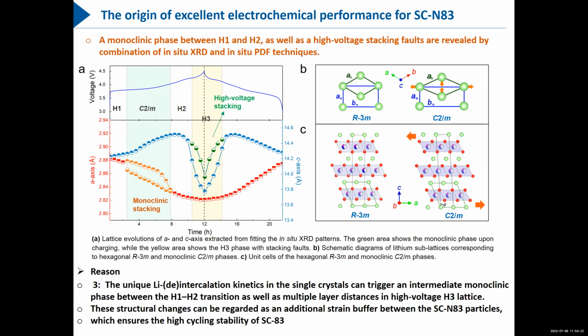I have studied hundreds of different kinds of NCM materials. I never found this behavior in polycrystalline materials before. Of course, I don't know the reason, but I have just found this phenomenon. That means the single crystal nickel-rich materials have a very unique lithium intercalation kinetics, which could trigger an intermediate monoclinic phase transition between the H1 and H2 phases, and also the high voltage stacking.